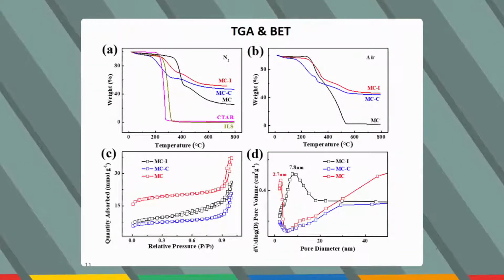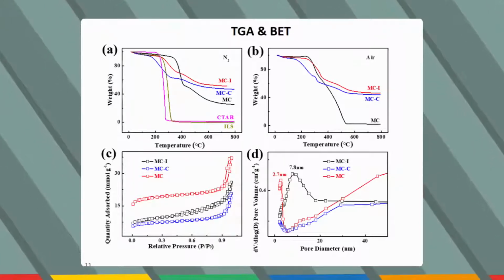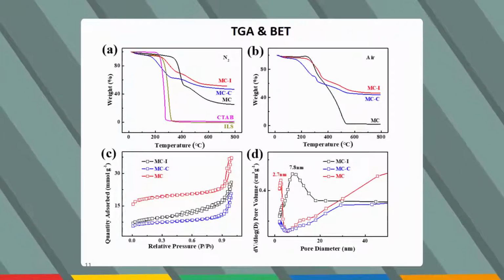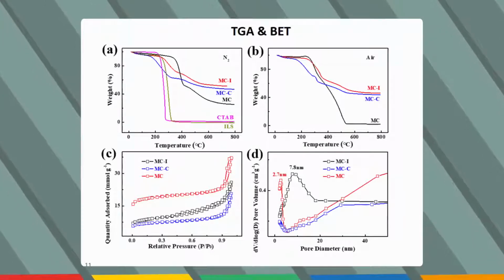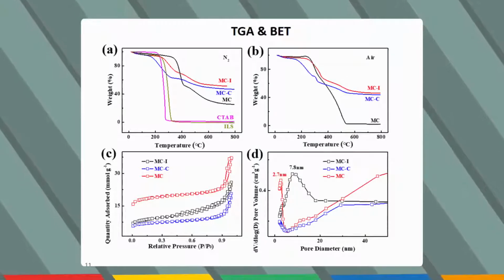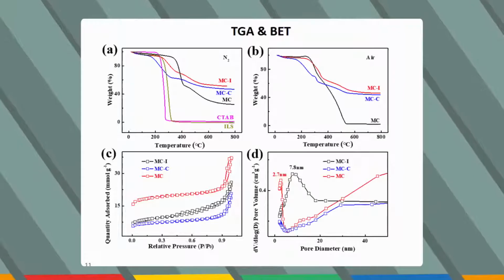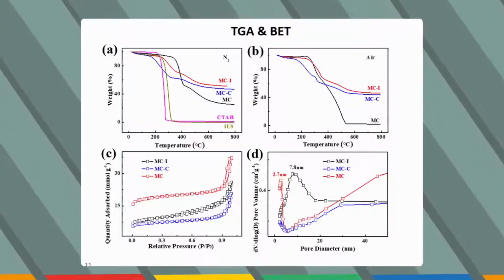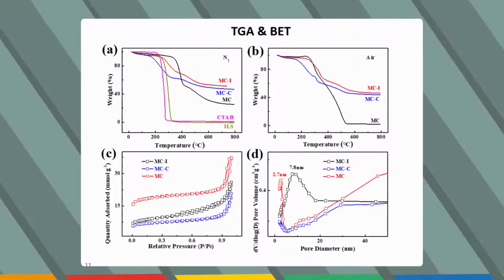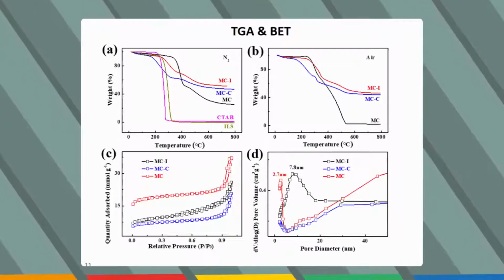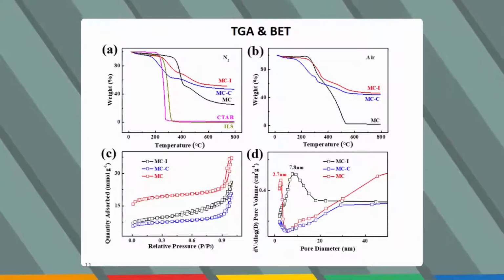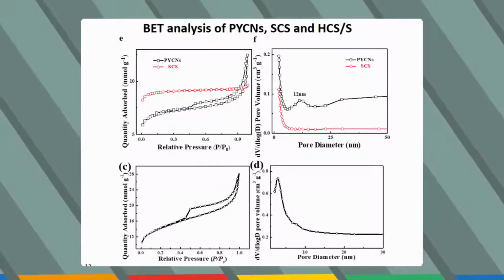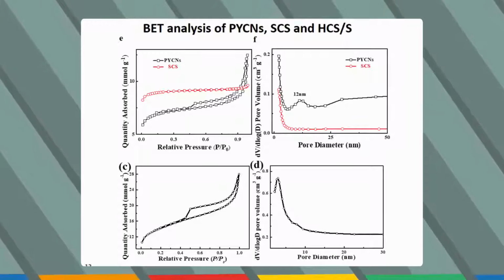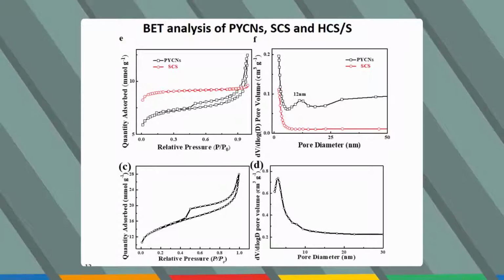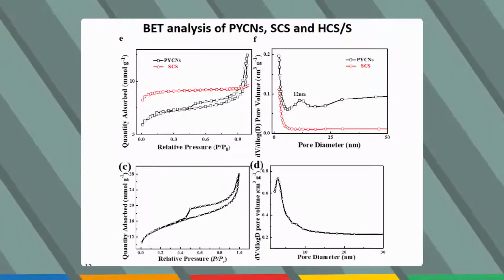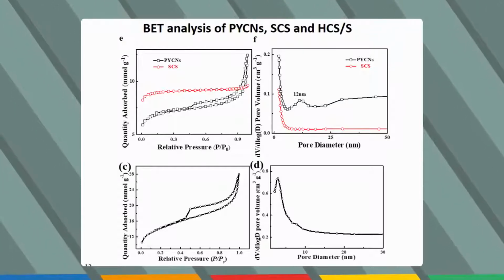We did different types of characterizations, but due to time, I did not include all the characterization techniques. The TGA just shows the decomposition of the materials under nitrogen and under air, and we can see the decomposition of the CTAB and ionic liquids at about 260 degrees Celsius. The nitrogen isotherms show very good materials that have regular pores and uniform size distribution. The solid carbon spheres and the hollow carbon spheres on the sheet also showed very regular and uniform pores, as well as size distribution, obeying the type 4 isotherm and the hysteresis loop type 3.